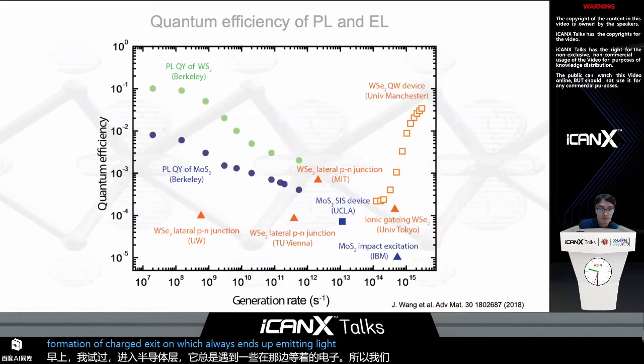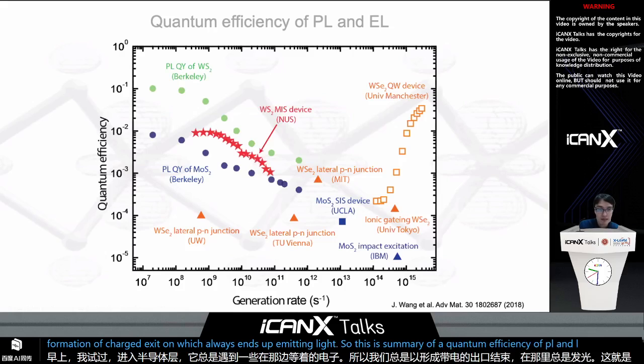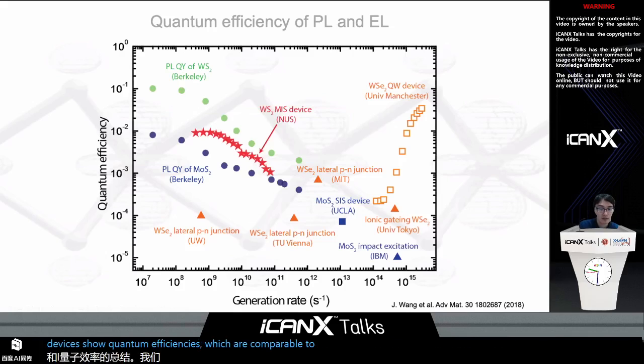So this is a summary of the quantum efficiency of PL and EL, and our devices show quantum efficiencies which are comparable to photoluminescence, which means that we essentially optimized the device configuration.